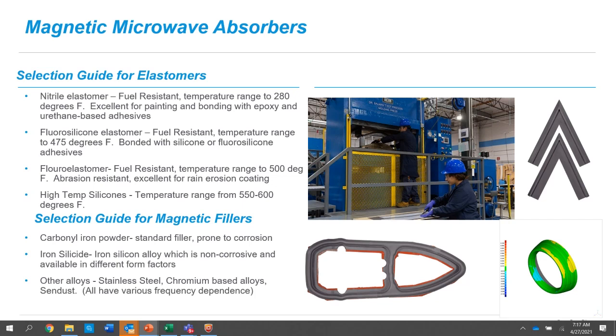For higher temperatures, we're doing a lot of work with fluorosilicones, both in conductive elastomers and absorbers, where we've actually released a series of absorbers in fluorosilicone. You have good fuel resistance again versus silicones, and then temperature ranges up to 475 to 500 degrees Fahrenheit. So a higher temperature solution, and again, they're usually bonded with either silicone or fluorosilicone adhesives, but have good affinity to that. They're certainly used on the exterior of vehicles and in large quantity production settings.